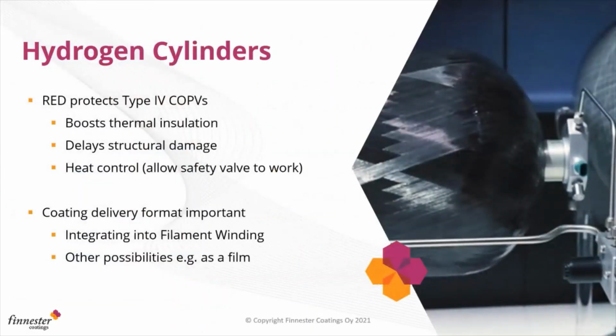When we go to the hydrogen cylinders, the red products will protect the type 4 hydrogen cylinders. How does it do that? It will boost the thermal insulation, so it will keep the heat out from the composite itself. It will delay the structural damage because there's no heat associated with the composite, and also it's a heat control. Of course some heat will be transferred, but in a controlled manner.